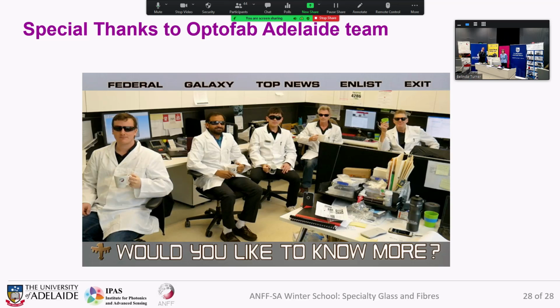Yes? Just noticing the air holes and the geometry is always symmetric to graded. Is there any advantage to just shifting it off the center? Yes, and we have done this for the exposed core fiber, where we completely shifted it to the surface, so that also the access is easier. This is an interesting example, because what we found is the fiber is fine, you can work with it, but because it's off-axis, often to integrate a sensing fiber with standard fibers, the telecom fibers, where the core is in the center, then it's not good to have an off-center core. That was the only reason for us now to make only exposed core fibers, where now the core is aligned in the center so that we can splice it to telecom fibers.